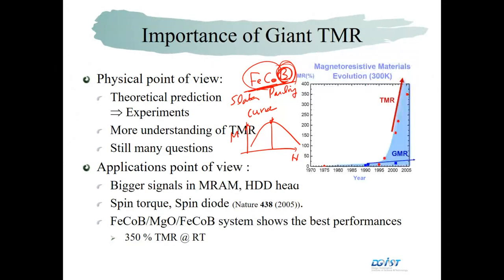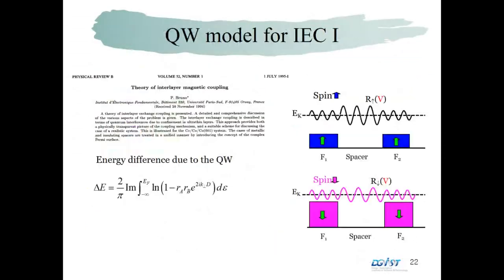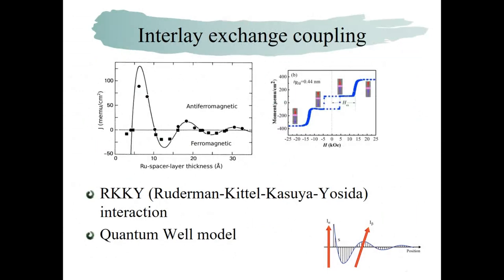Okay. So in an RKKY interaction, here zero thickness means two ferromagnetic layers just without any non-magnetic layer. So that means this is the atomic exchange coupling. Then it should be very large. So in this idea, if you have something like this value to be the atomic coupling strength, it is much larger than the interlayer coupling.